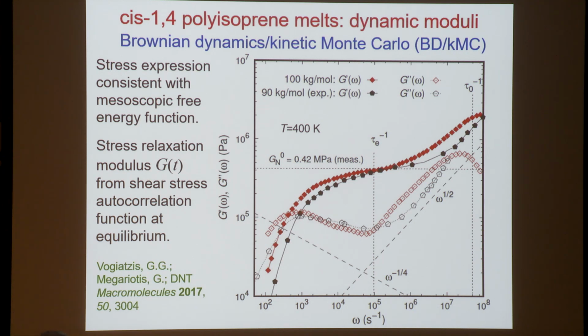We can also calculate the storage and loss moduli for melts which are subjected to oscillatory shear deformation. G prime and G double prime, they express the elastic and viscous response of the melt to this deformation. So here we see these results. They were obtained essentially by calculating first the stress relaxation modulus from the time autocorrelation function of the stresses, and then Fourier transforming it to get G prime and G double prime. The red symbols are the simulation for G prime with the filled and for G double prime with the open symbols. The black symbols are the measurement for a cis-1,4 polyisoprene melt of comparable molecular weight, and the agreement is quite satisfying, especially the fact that we can calculate these G prime and G double prime at low frequencies, low omega, which are completely inaccessible by molecular dynamics.